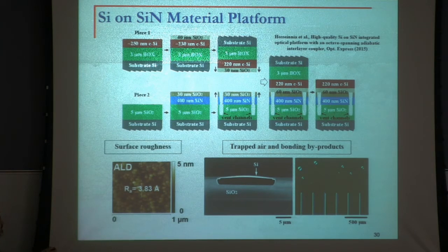Now these trenches are important. They are placed far from each other, like 500 micron from each other, which in integrated photonic language is a lot, because your device is tens of microns. We put them there because there are air bubbles that will develop at the bonding time if we don't. So you can easily see that when trenches are there, there are no air bubbles. When there are no trenches, there is an air bubble. And again, this took us about a year to optimize to the quality that is competitive and not sacrificing either silicon or silicon nitride property after bonding.